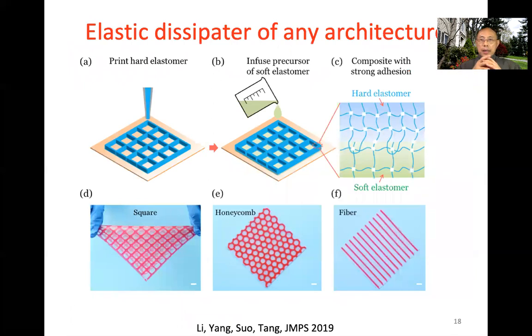So now the idea is also valid for not just fiber reinforced material. Here we made an elastomer using two versions of elastomer. We print one version, a stiff elastomer, and pour the soft elastomer as a matrix. So this is a sample prepared. This material is also fatigue resistant.